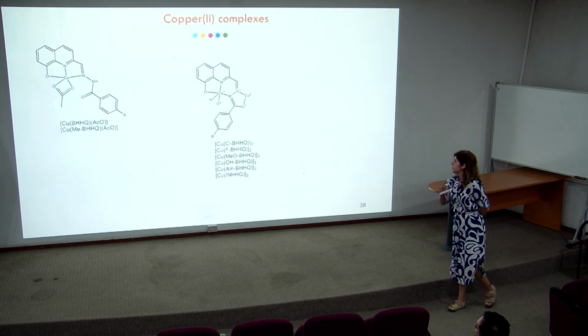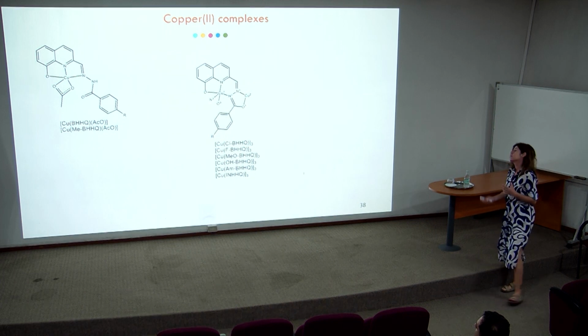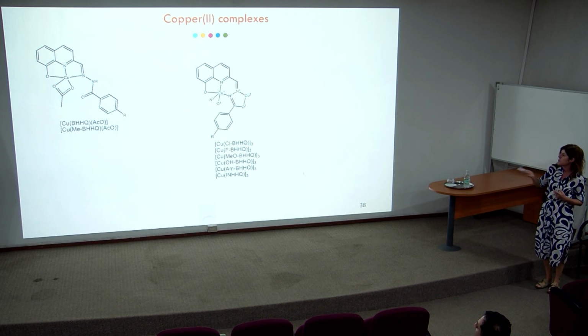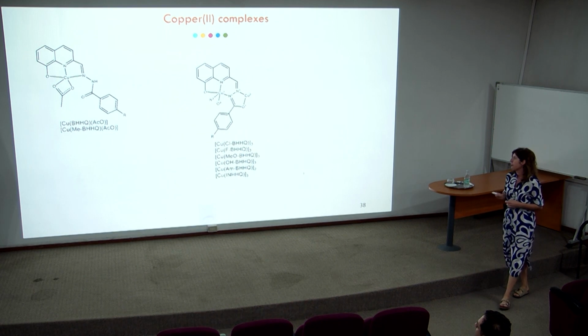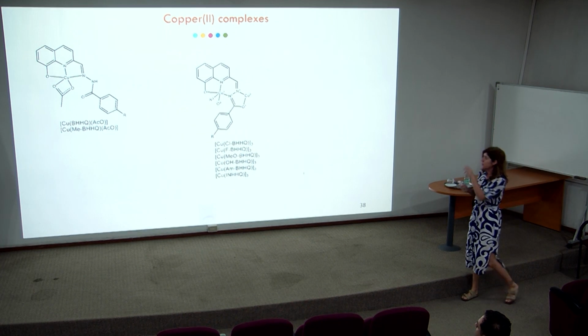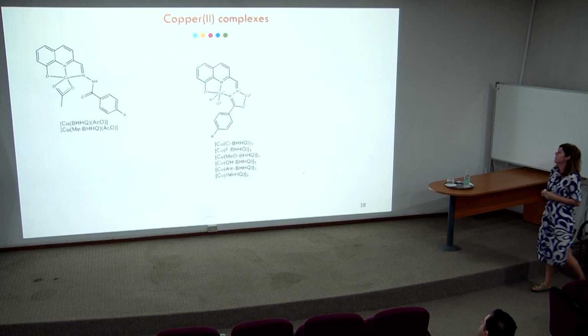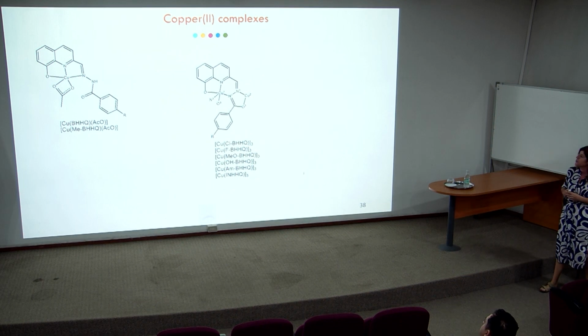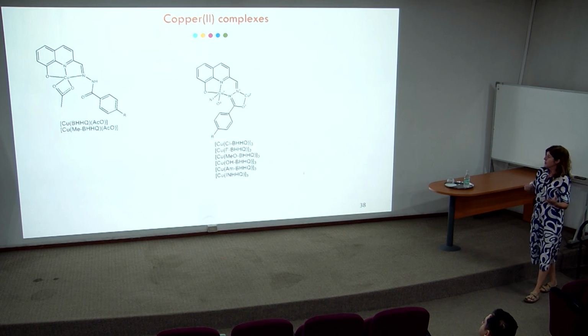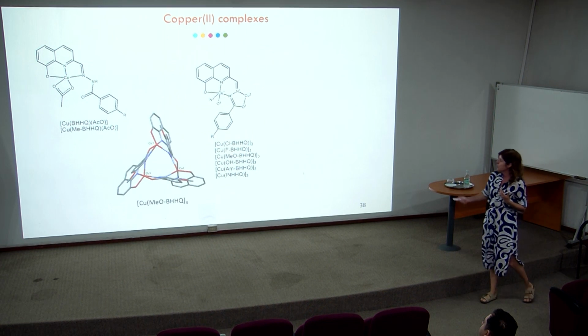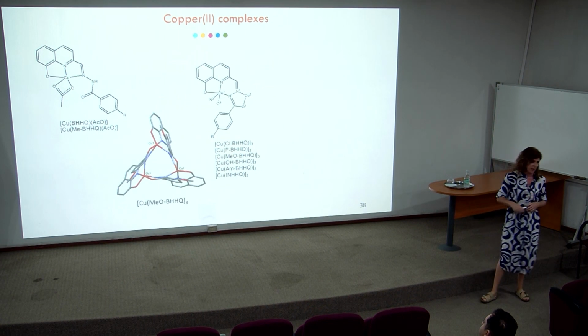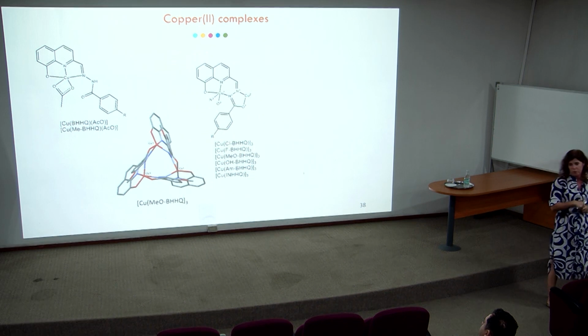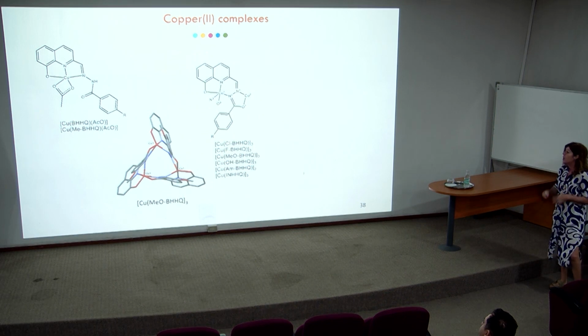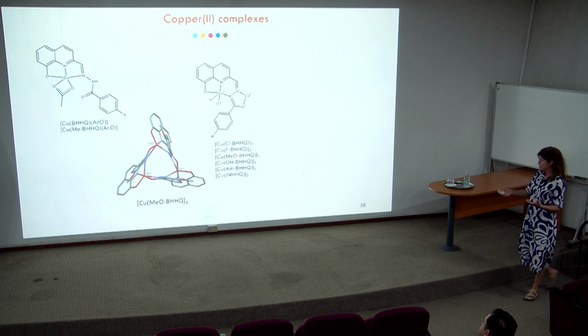So, for these ligands, we decided to use two different metal ions. I will speak a little bit about the copper complexes and then the vanadium complexes. Different structures were again proposed for different ligands, and for one of the complexes we could obtain a trimeric structure in the solid state, which we could corroborate that it's also formed in solution.